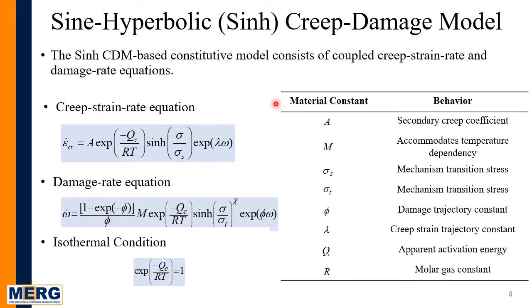Sine hyperbolic creep damage model has been chosen for this study. This CDM-based constitutive model consists of coupled creep strain rate and damage rate equations. The stress and temperature dependency are embedded into this rate-based equation, and these equations could be further simplified for the isothermal condition by taking this Arrhenius part equivalent to 1. And all the material constants are listed in this table, where few constants are fixed and others show stress and temperature dependency.